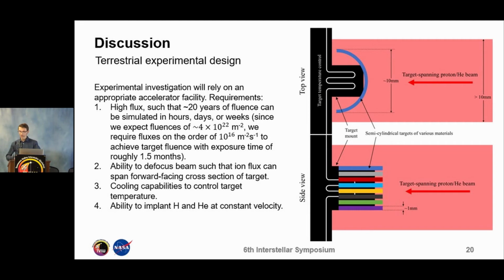Similarly, we would like the ability to defocus the beam such that the flux can span the entire forward-facing cross-section of the sample. Similarly, since we're looking for high fluxes, the temperature of the target will be a large problem, and so ideally we would have the ability to control the temperature of our target. Of course, diffusion depends greatly on the temperature of the target, so this will be an important aspect of an experiment. Additionally, it would be useful to implant hydrogen and helium simultaneously so we can observe the synergistic effects of implanting different species. We would also like to be able to perform material diagnostics on our samples after they have been irradiated, such as transmission electron microscopy and atomic force microscopy of the exposed surfaces, and then you can also use those things to determine the diffusion coefficients of various materials or various incident species on certain target materials.